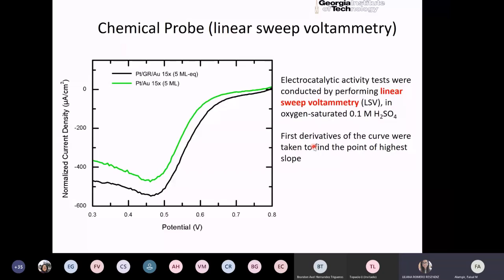All right. So then, as a way to investigate the chemical effects, we use the ORR reaction, the oxygen reduction reaction that I described before. And we are going to use this method called linear sweep voltammetry, where we sweep down from the oxidative potential towards the reduction potential, and we will look at the onset current of the reduction at the reduction potential. So that's a standard way of measuring the electrochemical activity of this catalyst.